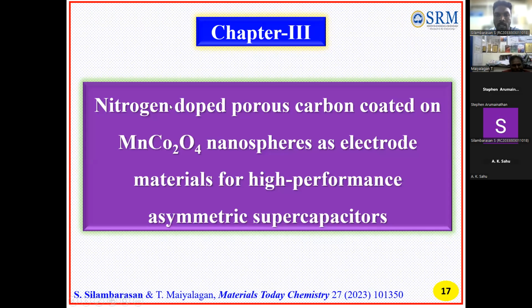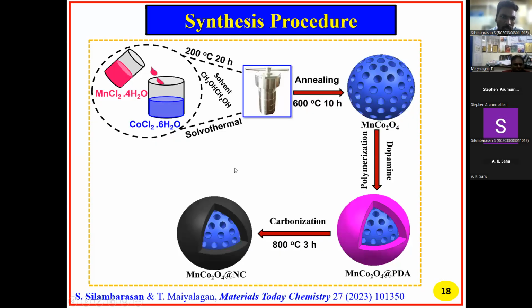Next, chapter 3, nitrogen doped porous carbon coated on MnCo2O4 nanosphere as electrode material for high performance asymmetric supercapacitors. In the synthesis procedure, we prepared by the solvothermal method using the precursors manganese and cobalt in a 1:2 ratio. Then using ethylene glycol as solvent, it is heated at 200 degrees C for 20 hours. Then finally, the prepared material is annealed at 600 degrees C for 10 hours. Then we got MnCo2O4 porous sphere.